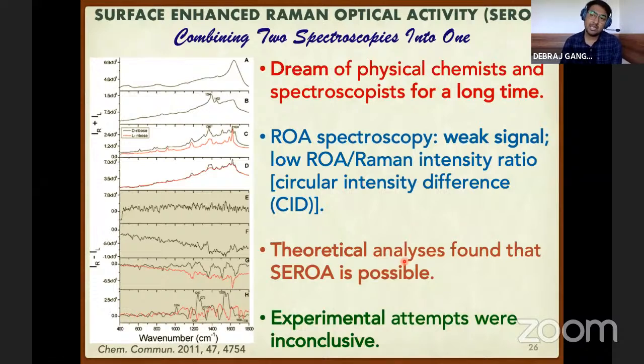Theoretical analysis done about 10 to 15 years ago found that SEROA is possible. They have some reports saying that SEROA is possible, but there were some experimental attempts, and all the experimental attempts were inconclusive. I have shown some of the experimental attempts here. This was published in 2011 in ChemComm, and you can see that these spectra don't look very convincing. Even for the enantiomers, they don't look exactly like mirror images. So it's a big question.